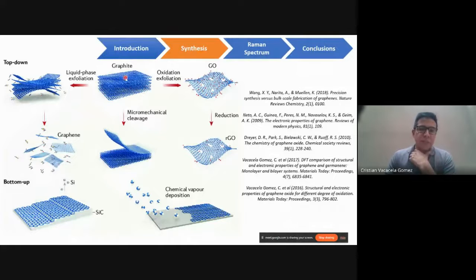Now, coming back to graphite, if we move to the left side, we can also use liquid phase exfoliation methods, where we introduce graphite in an organic solvent or water to produce few layer graphene or graphene nanoplatelets. Now, moving down to the bottom-up approaches, the most common method to prepare high quality graphene, single layer graphene, is chemical vapor deposition. But let me repeat again: in our group, we are interested in working with the top-down approaches.